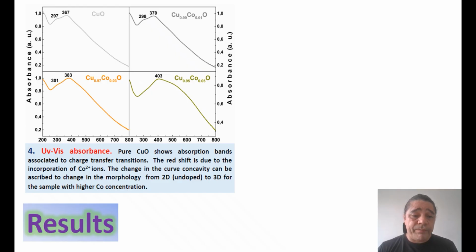UV absorbance. Pure copper oxide samples show absorption bands associated to charge transfer transition. The red shift in the cobalt copper oxide samples is due to the incorporation of cobalt 2 plus ions in the lattice structure. The change in the absorption edge can be ascribed to the change in morphology from 2D for the undoped sample to 3D for the sample with higher cobalt concentration.